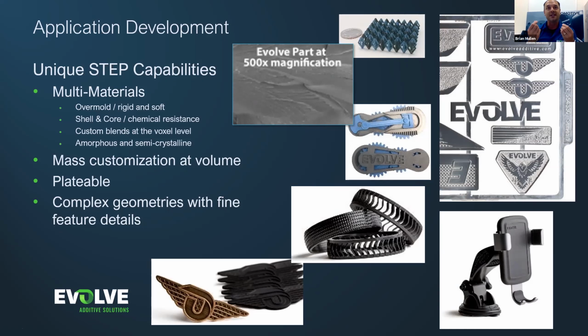You can also see from the SEM image in the middle here, 500x magnification. This is a cross-sectional area in which we have taken a part and broken it in half and looked at the cross section. You can see a fully dense material. So we do not have a lot of voids in our materials. They are fully fused. And as such, we have really nice impact strength and tensile strength properties.